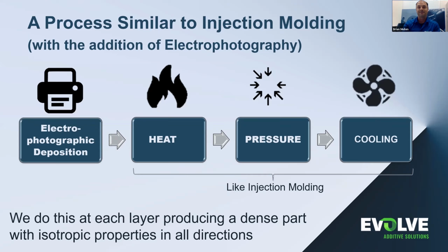process, and then we use that process over and over using injection molding-like types of processes in which we heat layers that are in two dimensions. We heat them above their glass transition temperature. We use pressure to fuse the images together, and then we cool them off below their Tg and we repeat. And this is done over and over, over 1,000 times until we get our 3D printed build. And then we move on to a post-processing step where we isolate the 3D printed parts.